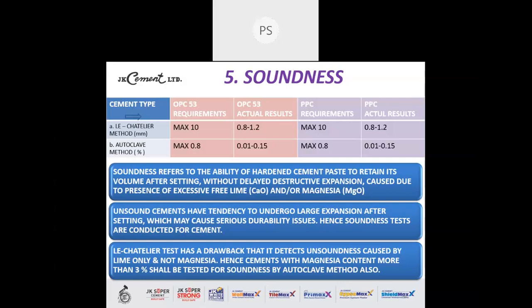Now, third point, Le Chatelier test. Why 2 tests? Why not only 1 test? Le Chatelier test has a drawback. It detects unsoundness caused by lime only and not magnesia. Hence, cements with magnesia content more than 3% shall be tested for soundness by autoclave method also. So IS code says that the Le Chatelier test has a slight drawback, and that is why cements with MgO more than 3% should be tested by the autoclave method also. Next please.